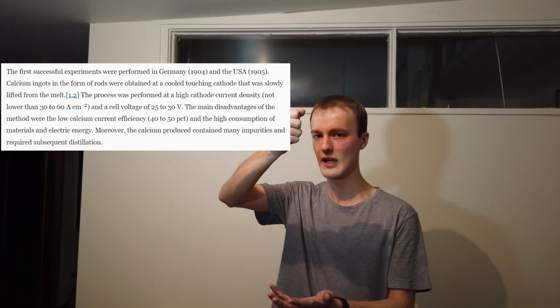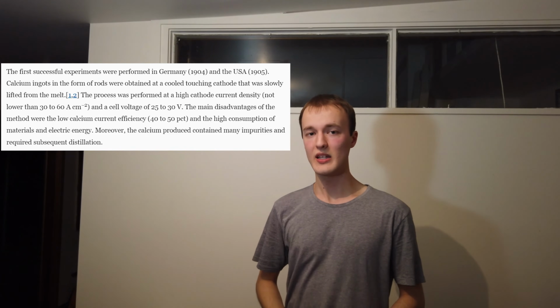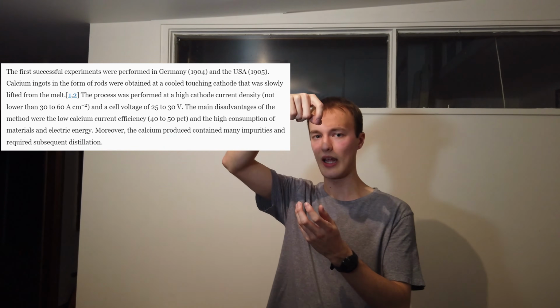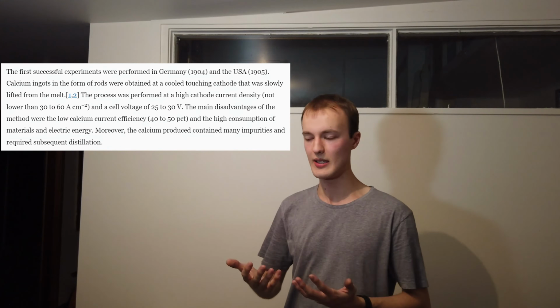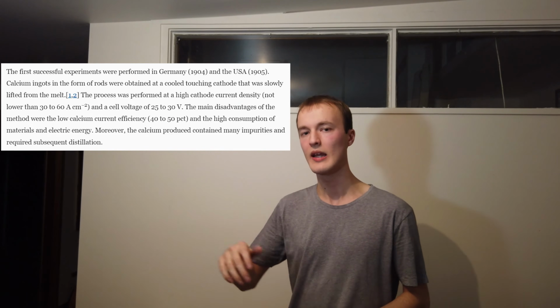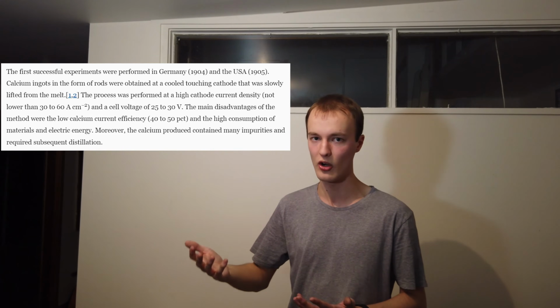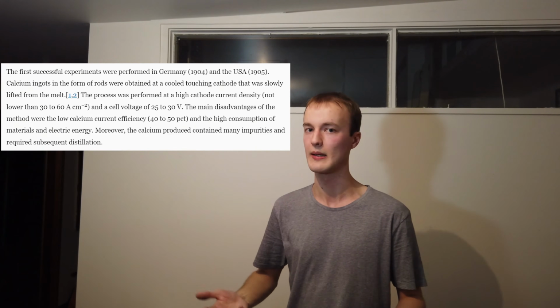The second thing we can do, most references state that the only successful industrial electrolytic calcium production has been done using a cathode that you kind of raise out of the cell as you're generating the calcium. The idea behind this is that by removing the cathode slowly from the melt, the calcium that forms on the cathode surface is removed from contact with the calcium chloride, which stops it from dissolving, obviously. Once again, basically every reference I've found seems to say that we require an inert atmosphere to do this, so my hopes for this reaction are pretty low.